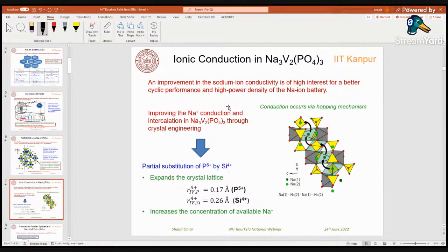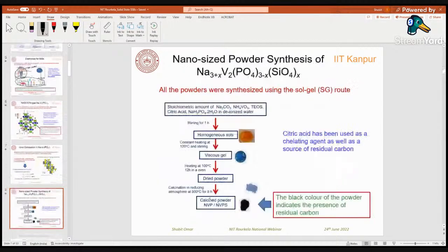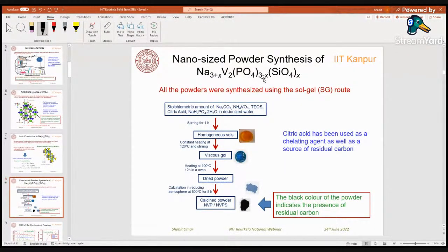What we have done, we have tried to dope this NVP material, and we did it by doping silicon on the phosphorus site. And why silicon? Because it has a similar ionic radius as phosphorus, a little bit larger than phosphorus, so it will expand the lattice, and that is what we are trying to do. We are trying to increase the interspatial channel space, and also we are trying to increase the concentration of sodium ion inside this material.